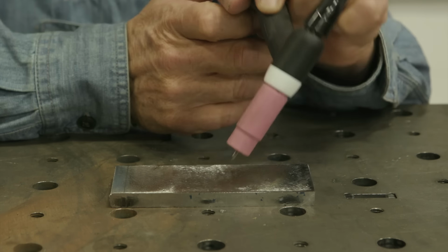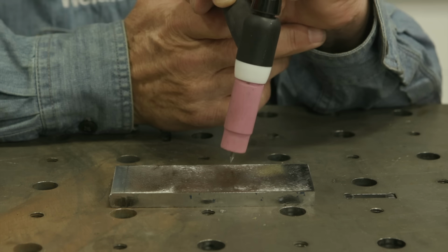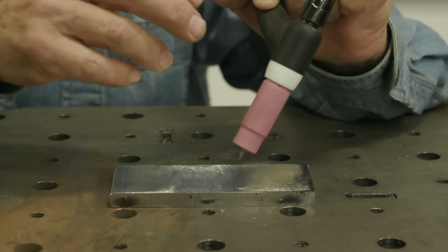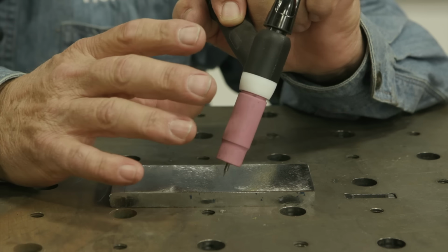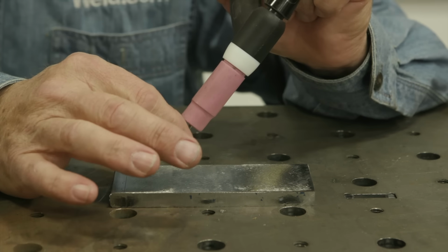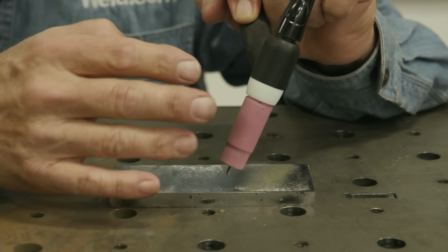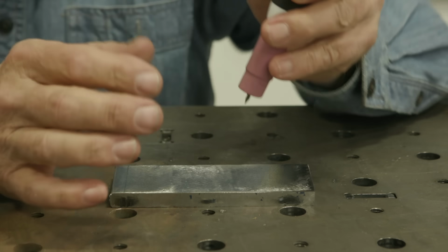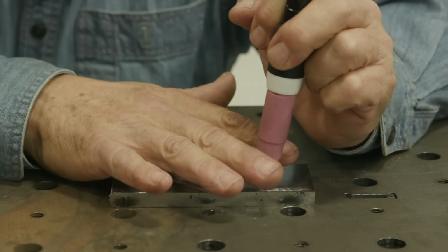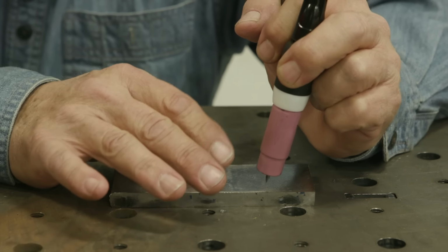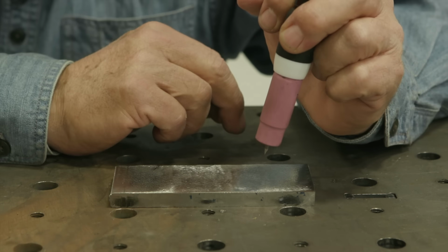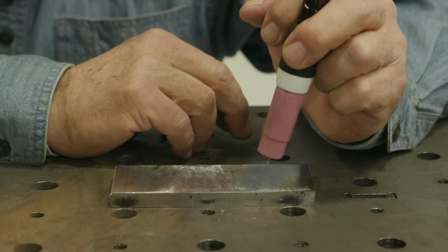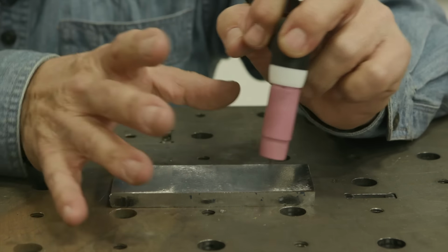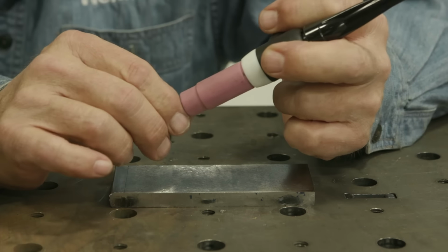Or they get too long of an arc. Okay, too long of an arc. The weld pool is not really underneath the tungsten. It's all over the place. And you have more of a chance of getting oxides in because your weld pool is outside of your gas shield. So we might be way up here. Things are going everywhere, okay?